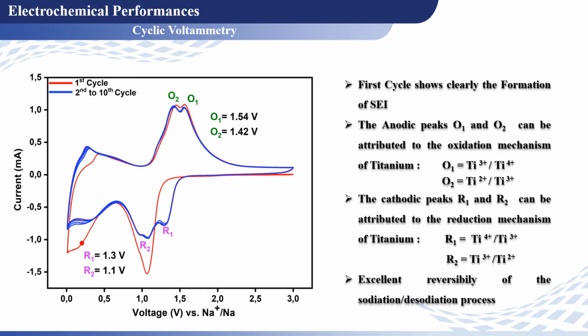Concerning the electrochemical tests, we have tested our material as an anode for sodium-ion batteries in a half electrochemical cell within the voltage window 0.01 volts until 3.0 volts at a current rate of 0.1 C. From the cyclic voltammetry tests, we can see a large primary cycle indicating the electrolyte's decomposition and the formation of a solid electrolyte interface layer. The 2 main anodic peaks observed at 1.54 volts and 1.42 volts are assigned to the oxidation process of titanium from 2+ to 3+ and then 4+, while the cathodic peaks observed at 1.3 volts and 1.1 volts are assigned to the reduction process of titanium.